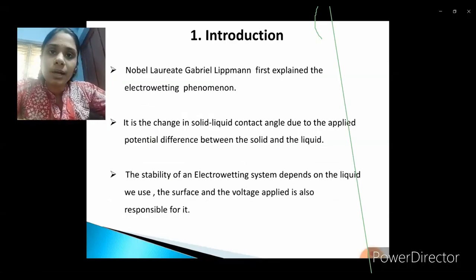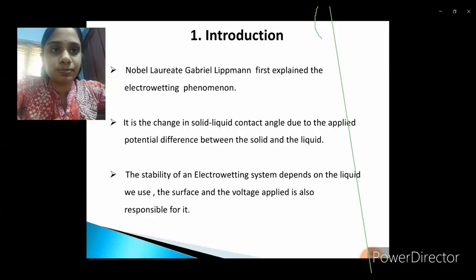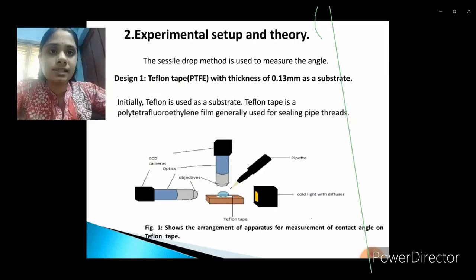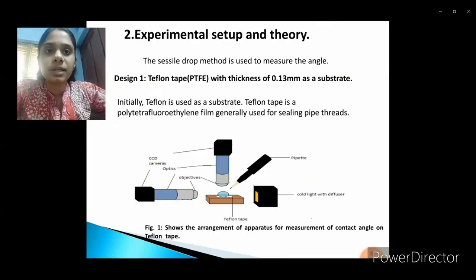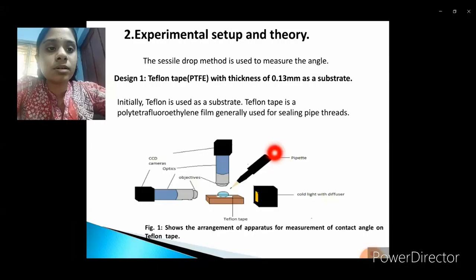Sessile drop method is used to measure the angle. We have used two substrates. First is Teflon tape, or polytetrafluoroethylene membrane, with a thickness of 0.13 millimeter. And the second one is the same polytetrafluoroethylene membrane, but the thickness is 0.005 millimeter. In this figure, we can see the arrangement of the apparatus. This is the platform on which the substrate is placed, and on that substrate a fine droplet of water is placed. The objective optics and CCD camera are used to capture the images of the droplet, and here is the light which illuminates the droplet.